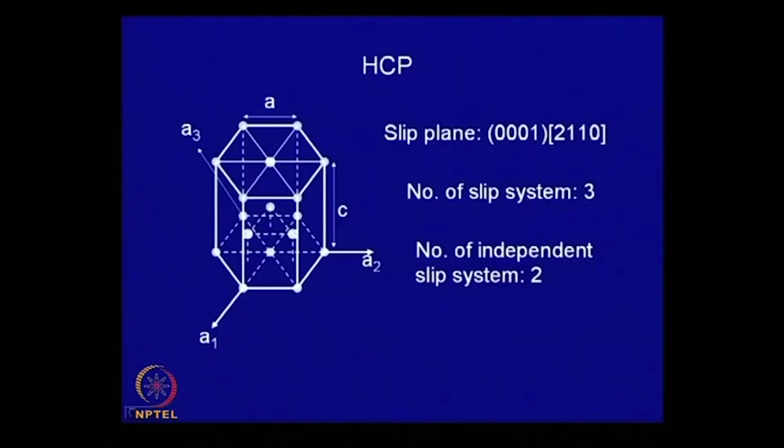Often few other slip systems also operate, these are prismatic slip systems. So, that means you join this and say this or similarly this. So, this is prismatic slip, but the direction is still the same, the direction is along these close packed directions, but that means you need additional slip planes, also you need an additional mode of deformation, that is twinning.